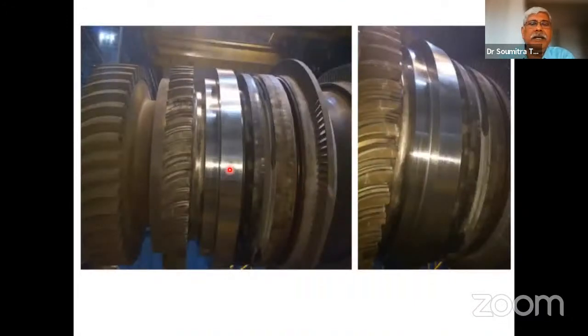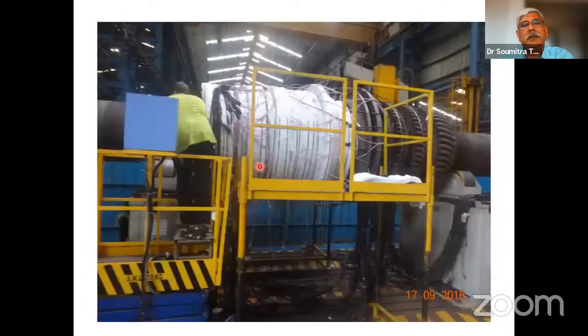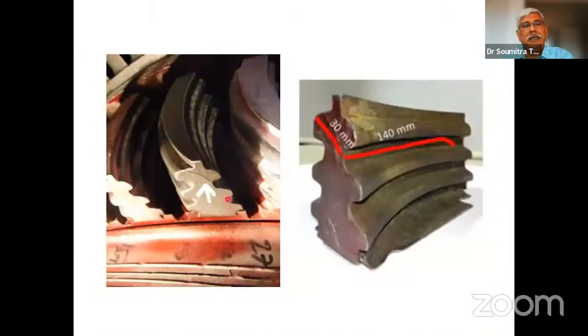This is after the welding, the final machining, when some defect was found and a local region had to be taken out and again rewelded, not to our liking, but nothing could be done. The post-weld heat treatment after the welding. This is the defect that was found in the existing fir tree in the disc, where the fir tree root for blade attachment is there.